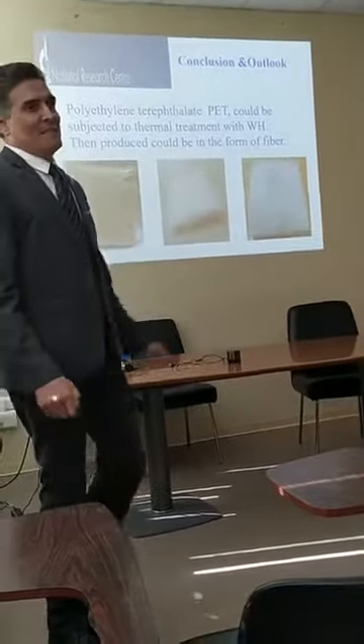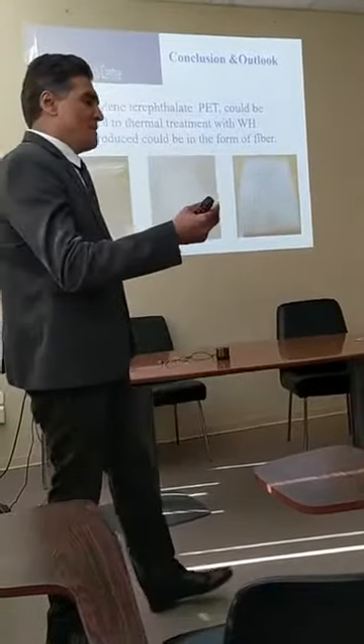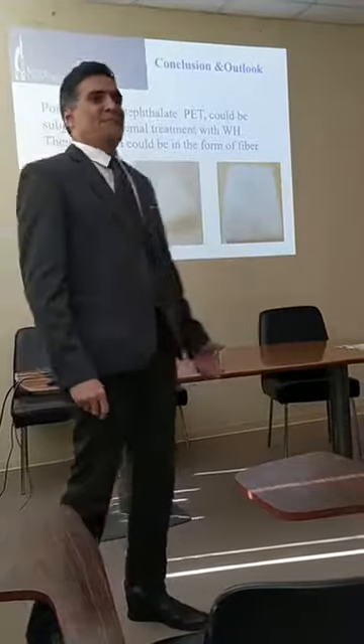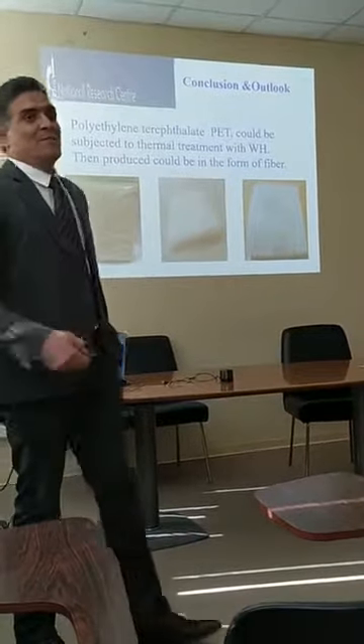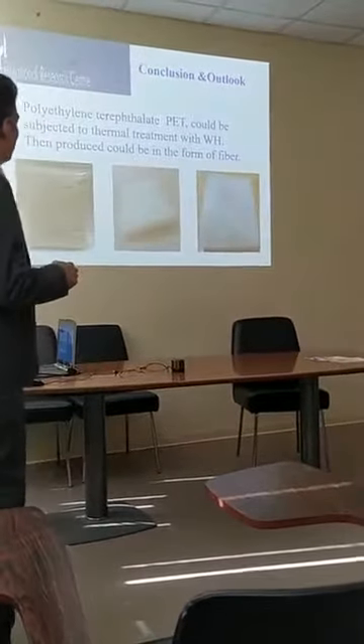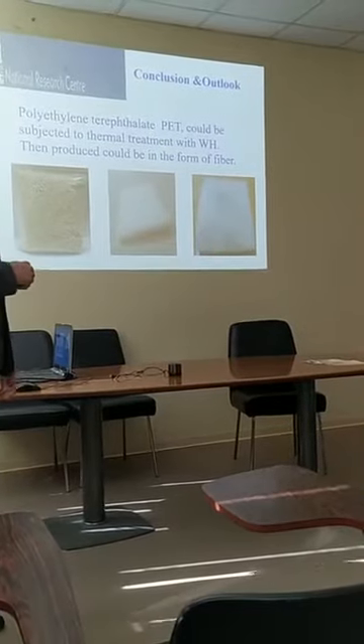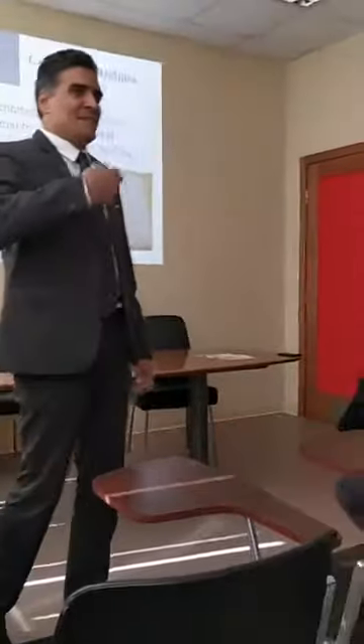Also, we have something a little bit different. We think that if you are going to make substitution, you make sodium alginate instead of chitosan. What about the cross-linker? Because cross-linker is very expensive. We think about polyethylene terephthalate, PET, which is also a waste. It's something like a plastic waste, like the plastic of water bottles we drink. If we make this plastic, do it like this with thermal treatment, we can further treat it thermally. You increase the heat up to 290, and then you cool it suddenly in water. Then you get some kind of foam like this. And then we got a functional group inside the foam.